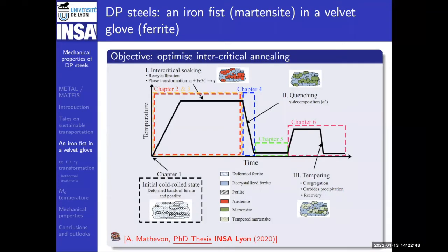So these dual phase steels are produced classically using this temperature time route. First, we go into the intercritical soaking domain to have a mixture of austenite and ferrite. Then we quench, and the austenite transforms into martensite. And then eventually we perform aging treatments, and the aim of this work is to